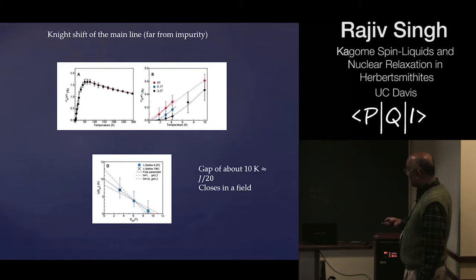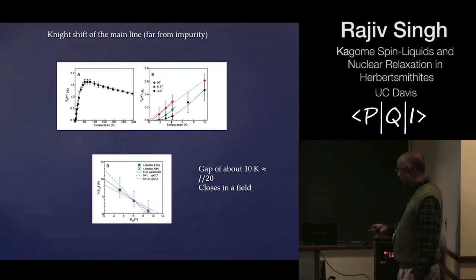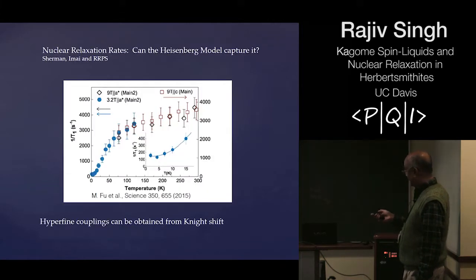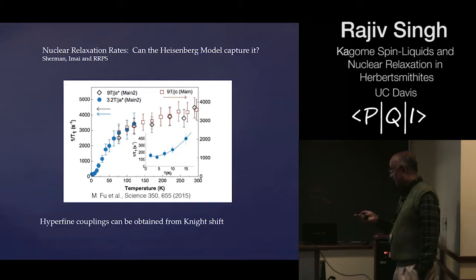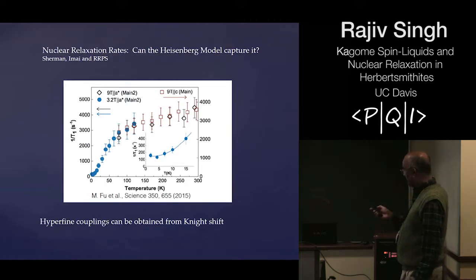One finds activated behavior as you expect for a gap, and that gap becomes smaller and smaller as you apply a bigger and bigger magnetic field. So this is the magnetic field and this is the gap, and you plot this, and then you can extrapolate down to zero field and get an estimate for the gap, which is actually quite consistent with a value of order J over 20. So this is really experimental evidence that the system actually forms a gapped spin liquid.